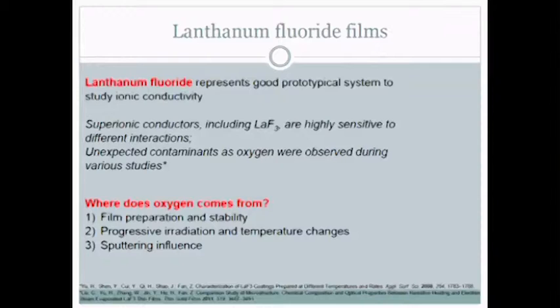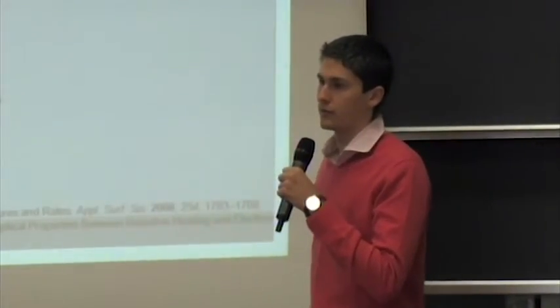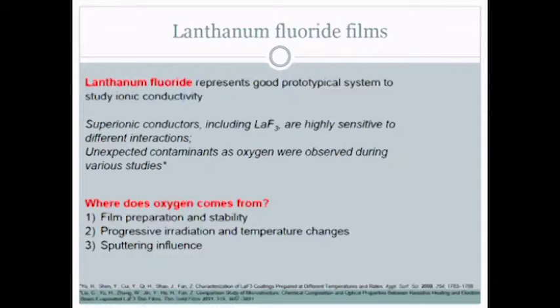But it was not so simple to study this material because of... In the previous year we studied these materials with the X-ray photoelectron spectroscopy technique. I will say a few words about this technique later, but this technique is only interface surface sensitive, only a few surface nanometers. And to study the depths of the film, so all the thickness of the film, we were forced to use sputtering. And apparently with depth, we observed an increase of oxygen inside of the film.